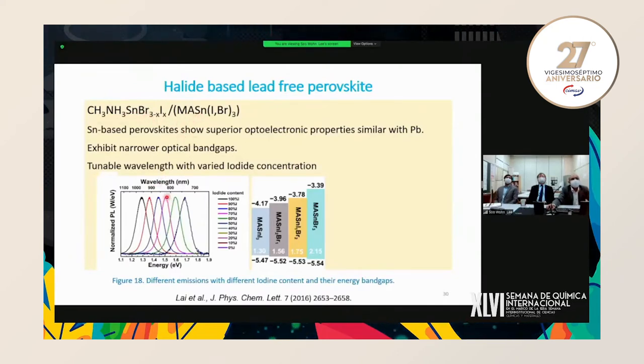It has some characteristic features, such as if we change the ratio of iodine to bromine concentration, we can have different emissions in NIR. Higher iodine concentration shows emissions around 1000 nanometers, while higher bromine concentration shows emissions around 750 nanometers. So we can tune the emissions with different concentrations of iodine and bromine in this perovskite material.